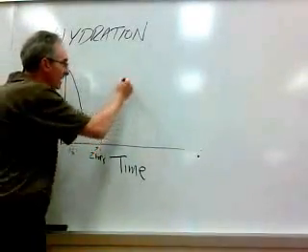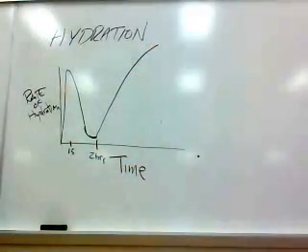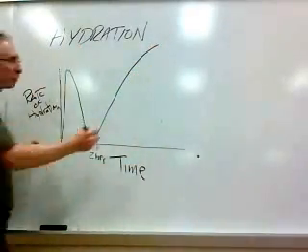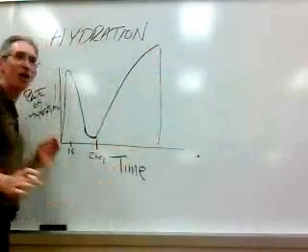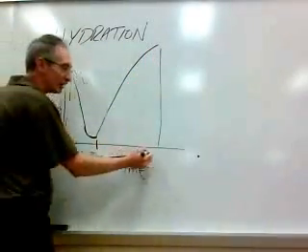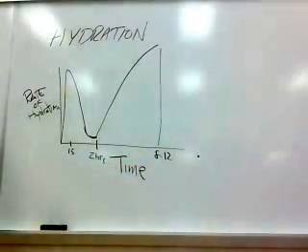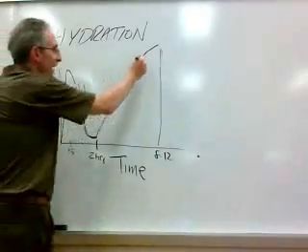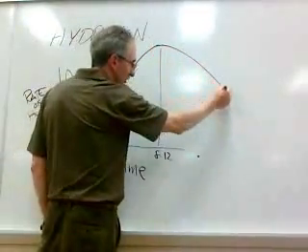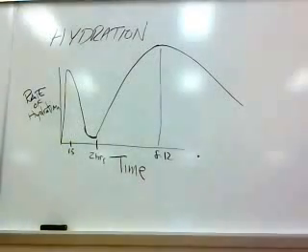All of a sudden, the hydration reaction kicks up again very quickly. And it peaks out, all these time values I'm giving are just general, but it peaks out in normal times maybe at 8 to 12 hours. Okay? And then at that point in time, it starts drifting downwards and downwards.